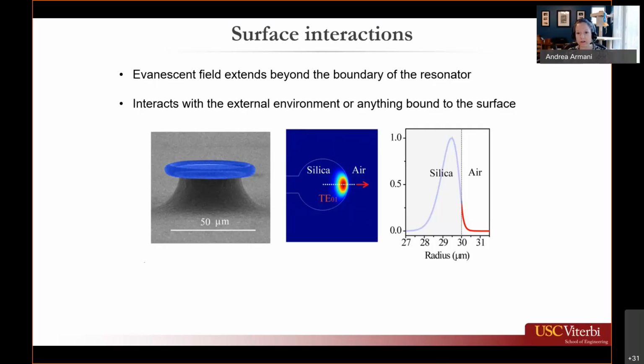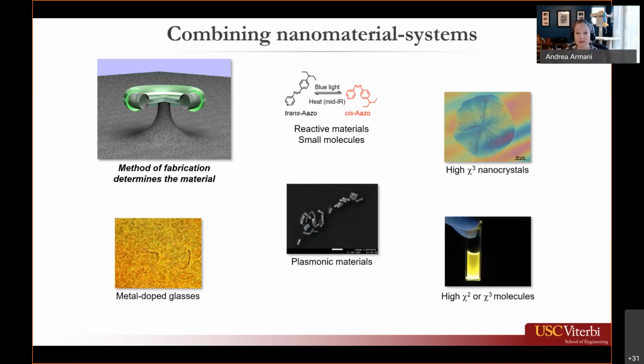And the shape of that evanescent field and the exact quantity that's located in the air is going to be dependent on the refractive index of the silica and the refractive index of whatever is attached to the surface. And I would say whatever the refractive index of the air is, although air is not really changing. So there are lots of different possible nanomaterial systems that one could investigate. You could think about looking at different types of small molecules, different types of nanocrystals, plasmonic materials, different types of Chi3 and Chi2 molecules. We've looked at pretty much all of these. Today I'm going to focus mainly on Chi2 molecules as well as reactive materials, so small molecules that can change their configuration when they're triggered with light. But a lot of these different materials can be investigated.